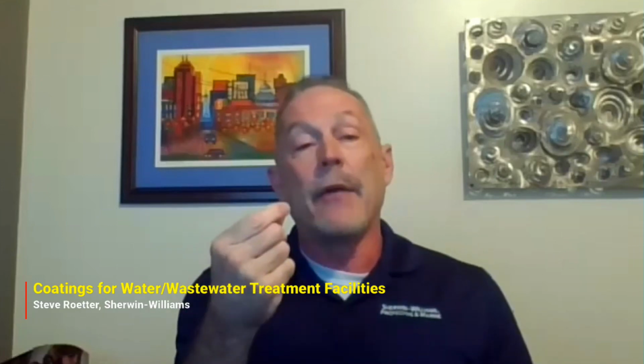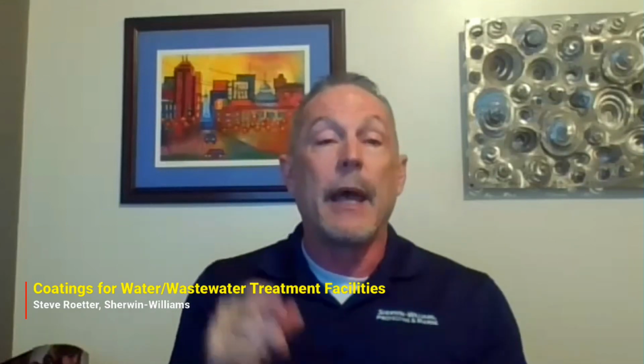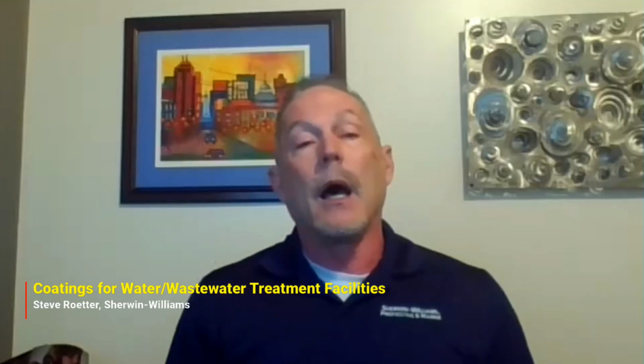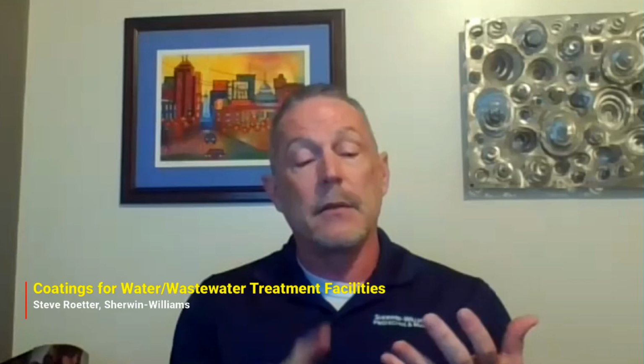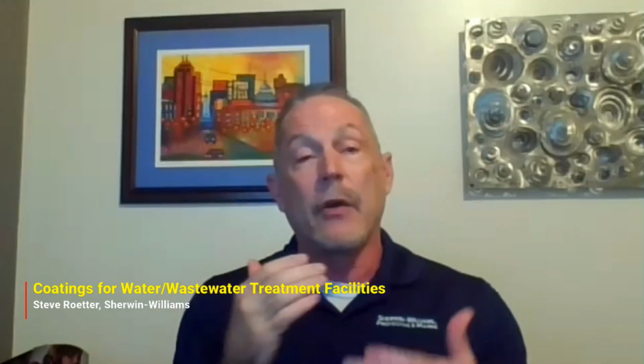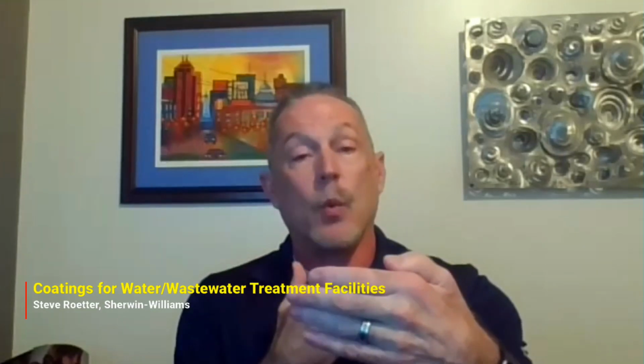One of the ways I've done in the past is I've actually taken concrete powder samples with a hammer drill. So you might drill down 1/8 of an inch, collect the powder up, put it in the bag, go another 1/8, put it in the bag. Send those samples to be tested by a lab for chlorides, sulfates, and pH. And you can sort of develop a profile in that concrete of how deep that penetration was. So you can tell a contractor, in general, we're going to remove an average of 1 inch of concrete from the surface when we do the repair.